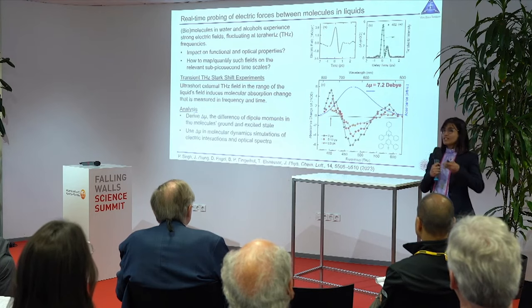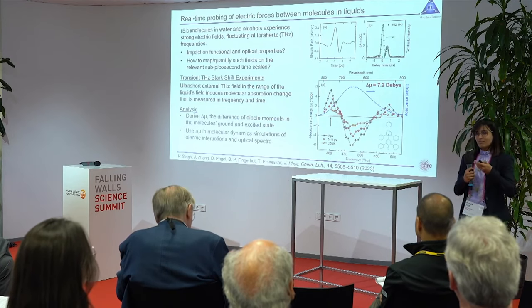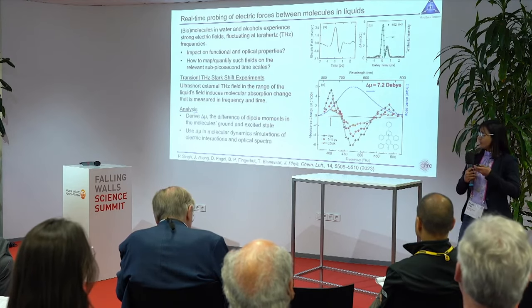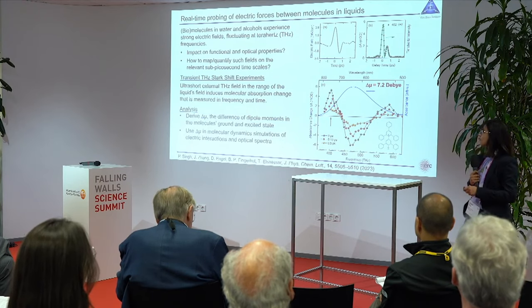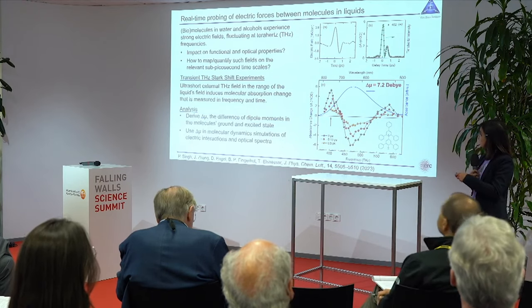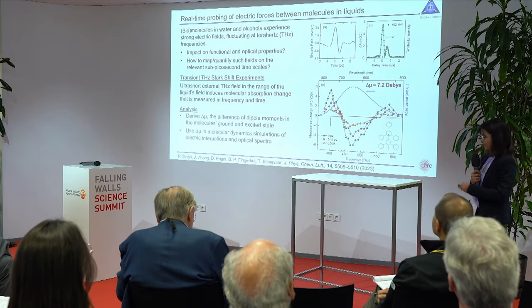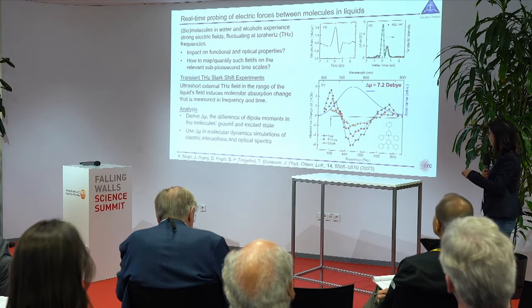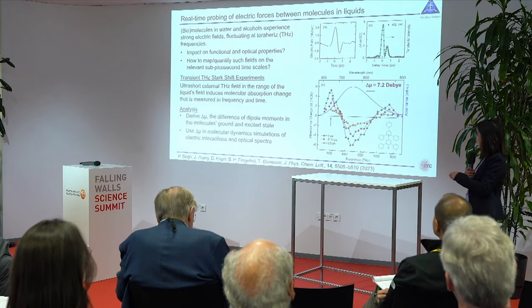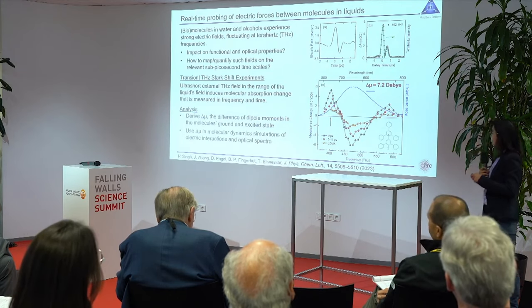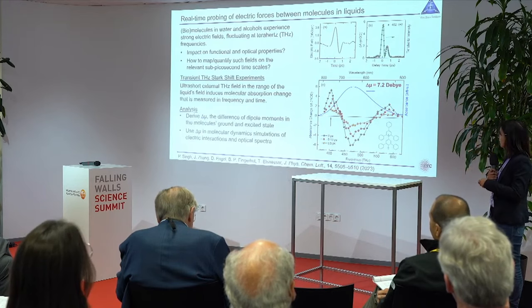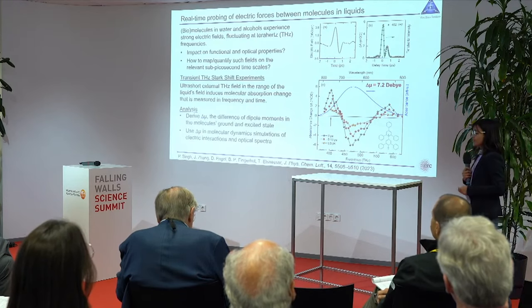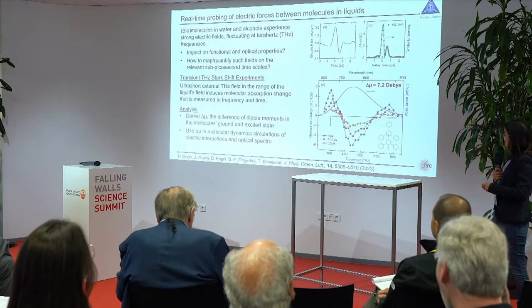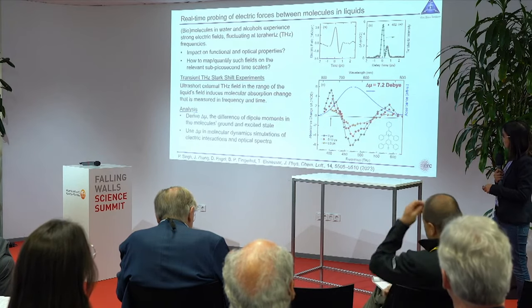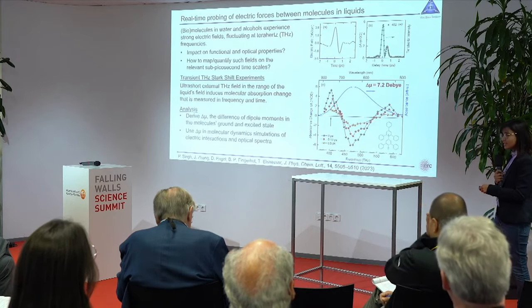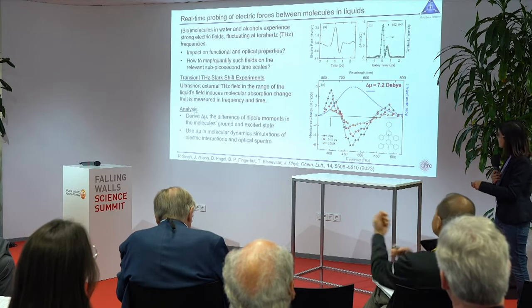Instead of relying on the fluctuating electric forces of the liquid environment, we make use of an external electric field, which is the terahertz pulses, as represented here. In the bottom main panel, we have the real absorption spectrum of our chromophore, which is given in blue. The terahertz-induced changes of this chromophore are given by the symbols. At first glance, we see a broadening in the system, which is manifested as an absorption decrease in the center and an absorption increase towards the edges.